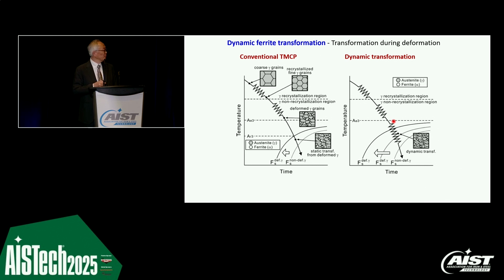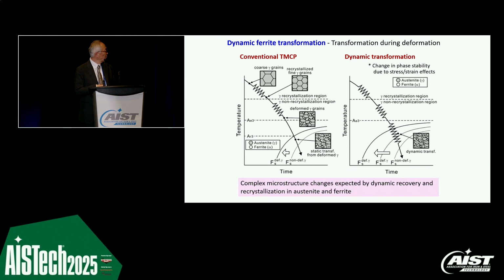We have deformation, phase transformation during deformation. As a result, because of the stress-strain effect, we have a change in the phase stability. We can transform the product above the transformation temperature. But simultaneously, we have the dynamic recovery or recrystallization of the austenite. So as a result, we have a very complex microstructure change, depending on the compression or processing condition. We have very complex phenomena in terms of dynamic transformations. But anyway, we have the new phenomena, transformation during plastic deformation.